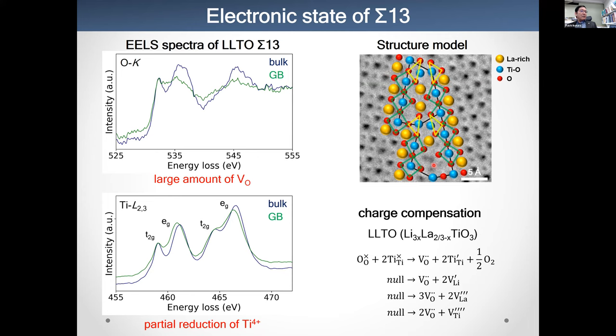And we again put in the octahedron. This green octahedron is also distributed. But in addition to this, you can see a triangular structure formed around titanium. So the coordination number of this structure is different. Probably the coordination number is 5. This octahedron is 6.